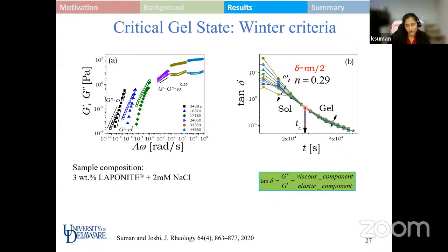So with the value of tan delta over here, one can estimate the value of delta, and the delta can be related to the relaxation exponent n using this formula, and we can compute the value of n to be 0.29. So the value of n computed using this scaling, using this law, and using the power law behavior of both the moduli is identical, which is 0.29. This is going to be a very important parameter because it relates all the major bulk rheological parameters, and we will see how it happens.